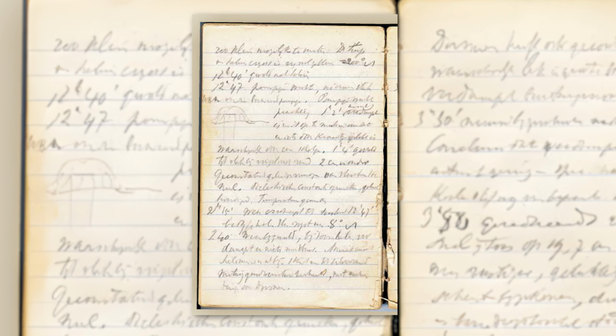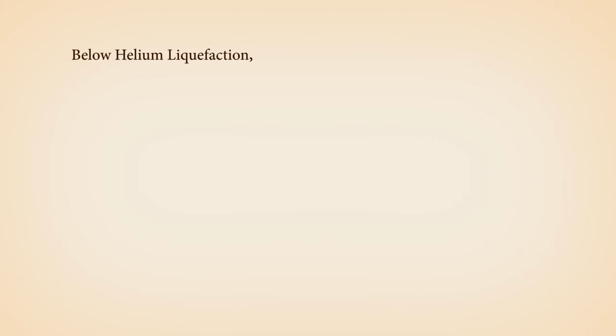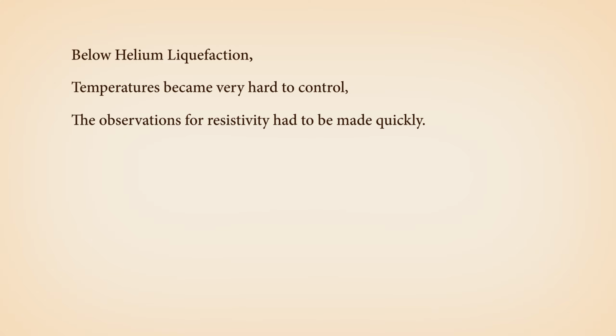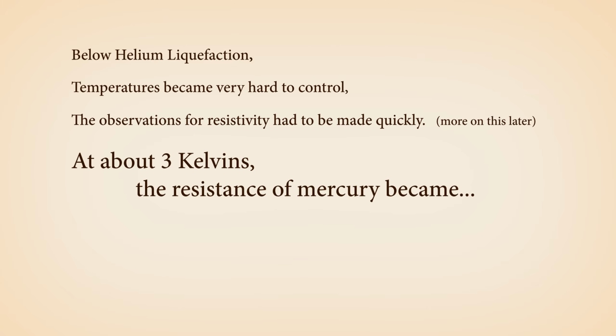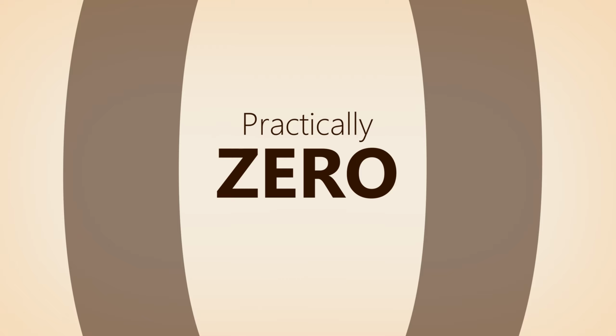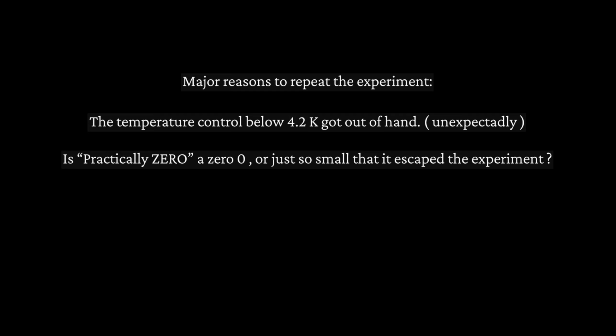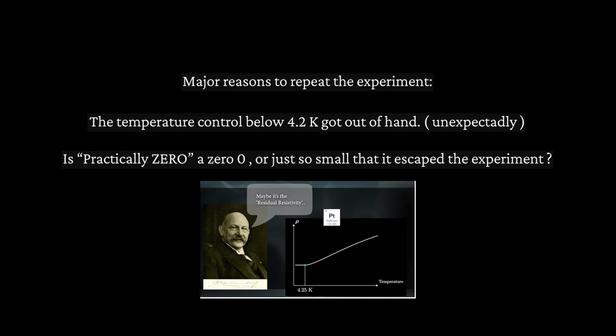Luckily, we have the original lab notebooks of the experiment and know what had happened. Below 4.2 kelvins, that is, the liquefaction of helium, the temperatures had become very hard to control, and so the observations of resistivity had to be made really quickly. More on this later. At about 3 kelvins, the lab notebook reports the resistance of mercury to be practically zero. Since controlling the temperature had become a problem, and practically zero could still be a very small but finite non-zero value, like the residual value of resistivity Onnes was thinking before, further experiments were done to seek clarity on these three queries.